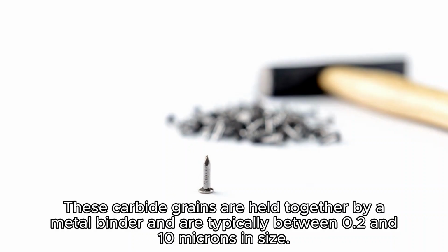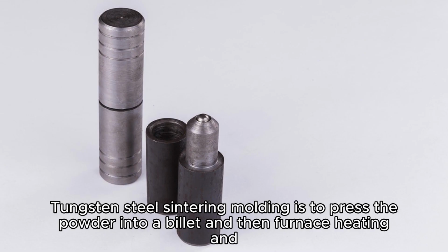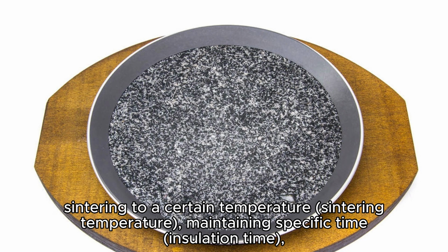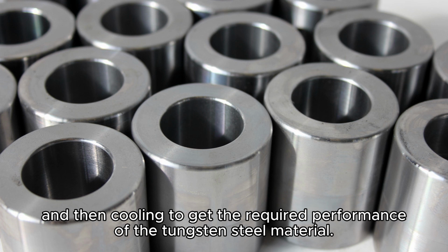These carbide grains are held together by a metal binder and are typically between 0.2 and 10 microns in size. Tungsten steel sintering molding is to press the powder into a billet, then heat it in a furnace and sinter it to a certain sintering temperature, maintain it for a specific insulation time, and then cool it to get the required performance of the tungsten steel material.